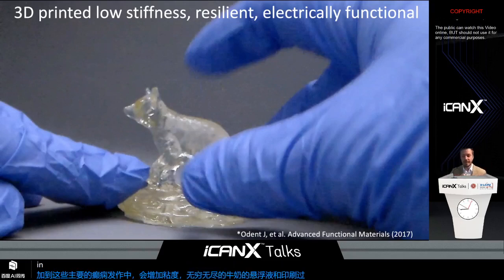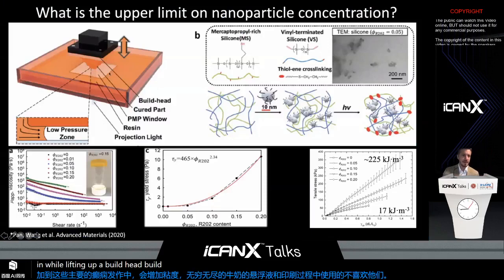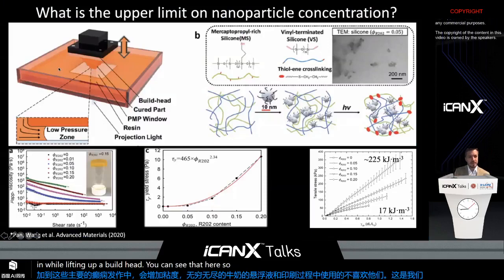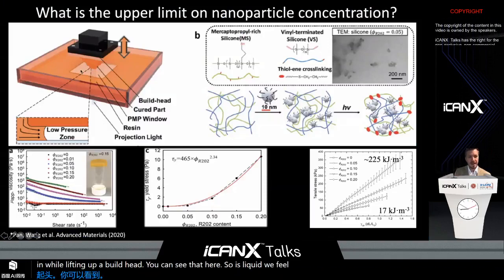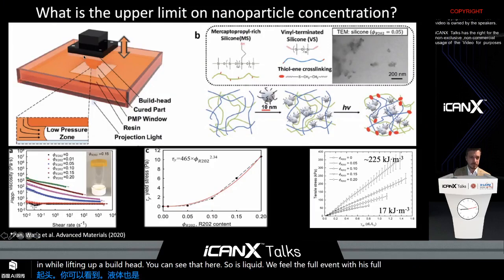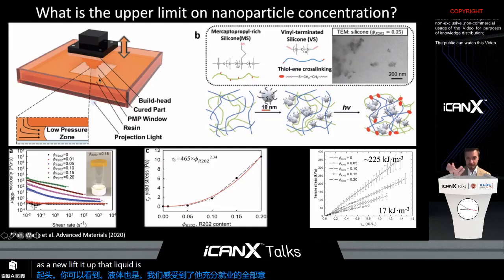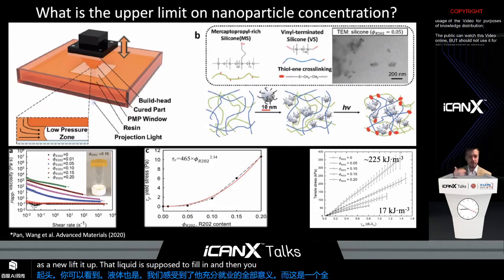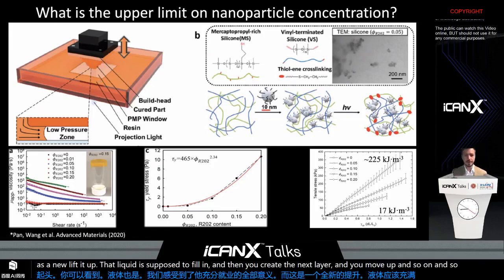We rely on liquid to flow in while we're lifting up a build head. You can see that here. So as liquid, we fill a vat with this photopolymerizable resin, and this build head is in it. And when you lift it up, that liquid is supposed to fill in, and then you print the next layer and you move up and so on and so forth until you have your part.